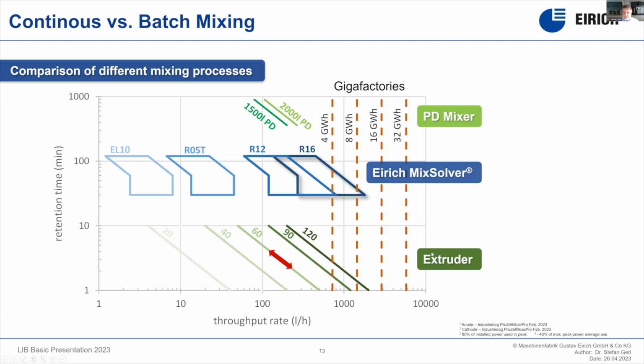On the other hand, we have the extruders, which have a retention time in the range of 1 to maybe 10 minutes. They can produce an output in the range of small to medium-sized gigafactories, depending on the size. But they are limited in flexibility, because if you want to change over the product, you also have to change the screw, for example, or screw geometry. The Eirich mixer is capable of running in a wide field because we can control the batch size and the batch time. If we don't need so much capacity, we just make 1 batch an hour instead of 1.5 or 2 batches an hour, and just wait in between until the next batch is necessary. But by this, we can make the same quality.